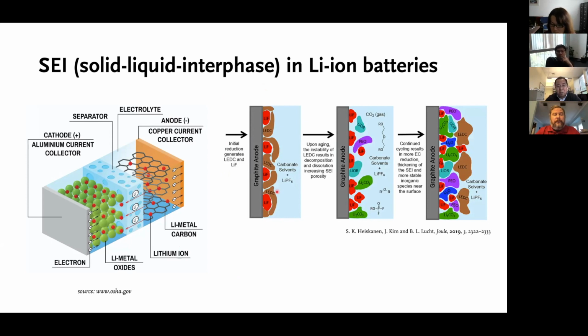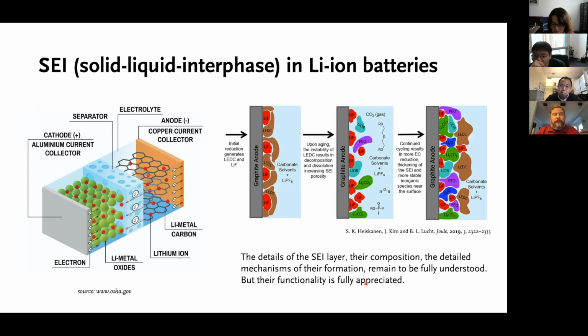It's about 10 to 20 nanometers thick. And this is a result of the initial reaction or decomposition of the electrolyte. The common electrolytes used are organic carbonates, ethylene carbonate, dimethyl carbonate, diethyl carbonate, for instance. And of course, there is also a salt. That's where the fluorine comes from. Lithium hexafluorophosphate, for instance, is a common salt used. What people realized is that upon the initial electrochemical reduction, the electrolyte, both the solvent and the salt, could be decomposed and deposited on the surface. And this layer, to this day, is not fully understood. But if it was not for this layer, we wouldn't have seen today's success.